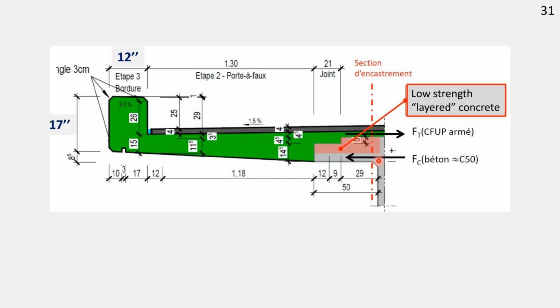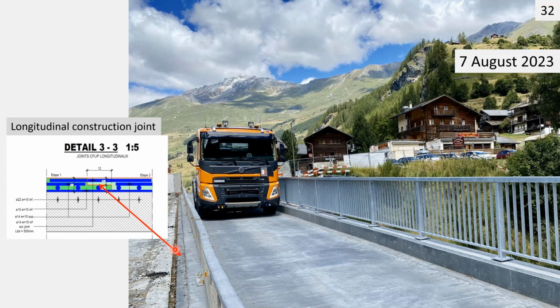Still on August 7, yes, this slide shows the working joint in the longitudinal direction. Of course, this has to be done in such a way that the working joint will be watertight. And the structural detail we use for many years in Switzerland is a lapped joint with a horizontal contact surface where a bond is created between the two UHPFRC layers that are consecutively cast. And this guarantees actually a waterproof joint, which we verified, by the way, by means of testing.